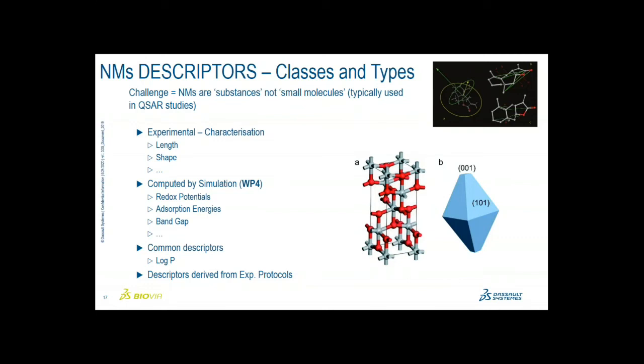So think carbon nanotubes would have a distribution of length, or if it's a nanoparticle, you might have various sizes, and so you have a particular size distribution to take into account. So that is really tricky. And also the experimental technique to characterize precisely the size, shape, length, and so forth of those nanomaterials is not always perfect. And we do have some, again, not experimental error as such, but deviation in the measurements.